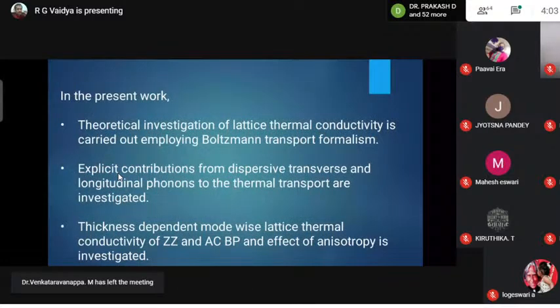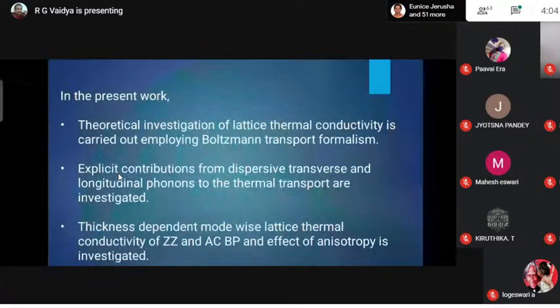In the present work, we have done the theoretical investigation of lattice thermal conductivity employing the Boltzmann transport formalism. We have studied the explicit contributions from dispersive transverse and longitudinal phonons to the lattice thermal conductivity of black phosphorus. And also we have carried out the work on thickness dependent mode wise lattice thermal conductivity of zigzag and armchair black phosphorus, and the effect of anisotropy is also investigated.